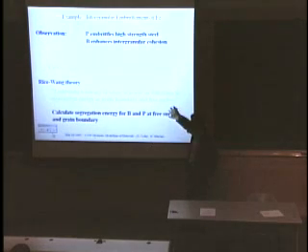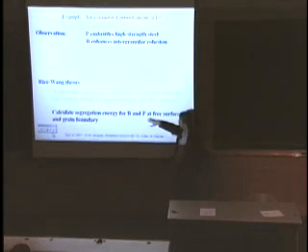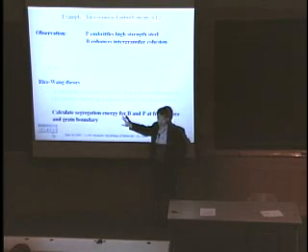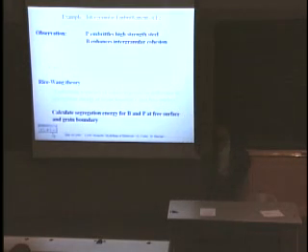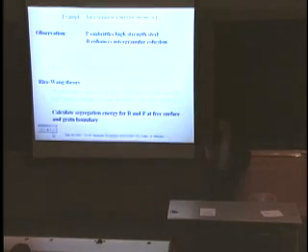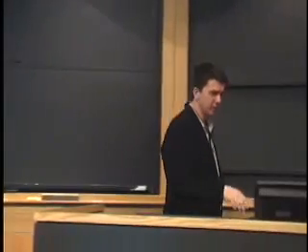But you can see why this is true from a driving force perspective. If you have an impurity that has a large segregation energy to a surface rather than a grain boundary, then its presence is going to enhance surfaces, because then it can have that benefit from that large segregation energy. So those are going to be embrittlers, because they will tend to promote decohesion. Whereas the ones that have a very large segregation energy at the grain boundary rather than the free surface will tend to promote cohesion. And so if you believe Rice-Wang theory, then this problem is very simple.